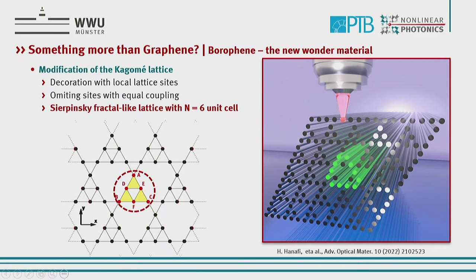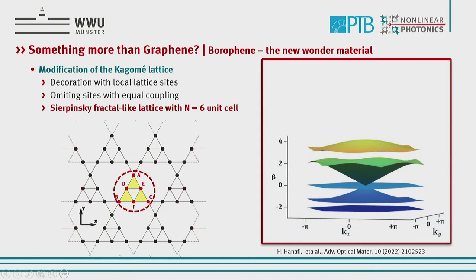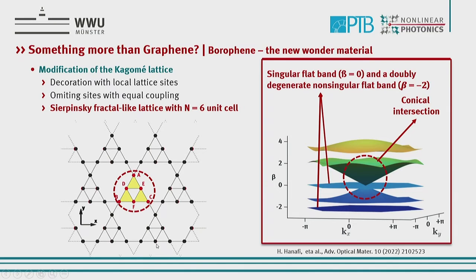also is connected to a lot of features in the band structure. And one of the features is that you have conical intersection again, but you have two different flat bands. And then you see this flat band here down. This is a flat band that is always connected to conical intersection, but this is a completely isolated flat band. It's also called non-singular flat band. And this is one that is so striking that during propagation in that band, no change, no dispersion, no diffraction will happen at all. So this is a very stable structure, and this is in this modification of the Kagome lattice to get this Sierpinski lattice.